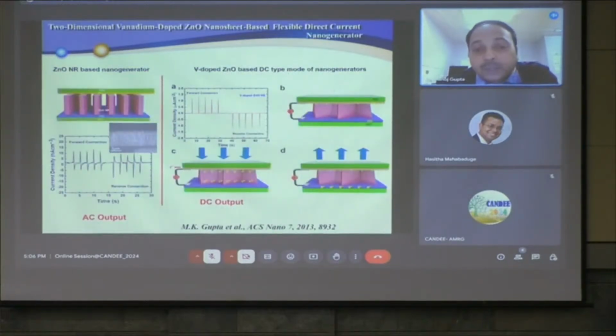Okay, so now coming to the nanogenerator fabrication. We basically need 2 electrodes. One is the nanorod grown on the ITO substrate, and another we need is one Schottky contact. So we chose the gold-coated PES substrate, where gold was coated on the plastic substrate so that the whole device is flexible and also transparent, at least this zinc oxide nanorod.